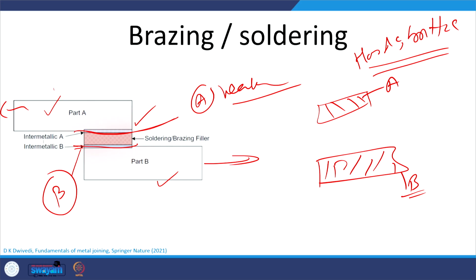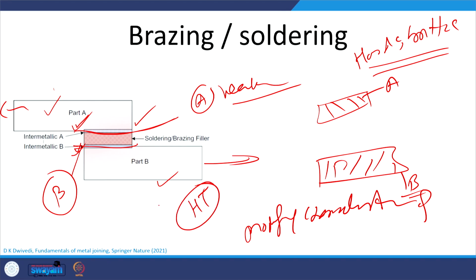So, what is done in order to modify the characteristics of the intermetallic being formed on the A side, intermetallic A or intermetallic B, we can do a lot of things. It includes the post heat treatment of the joint, or it also includes the modification of composition of the IMC which is being formed. So, that can be done by choosing the suitable kind of filler or by incorporating certain alloying elements with the filler. So, that helps in developing more appropriate kind of intermetallics wherever the failure is getting triggered.